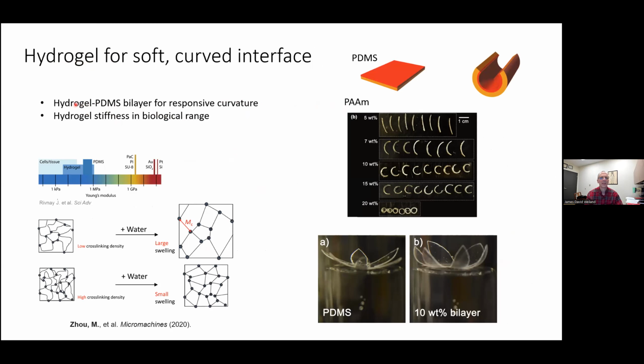So what we developed is a bilayer, hydrogel PDMS bilayer. These are two different materials, and the hydrogel is responsive when it's placed in water, as shown here. If you add water to a hydrogel, essentially it swells. And that's what we show here: when we control the amount of the hydrogel in our material, we can produce this curved substrate. And it works as follows.